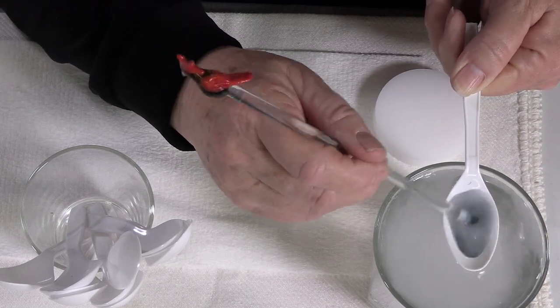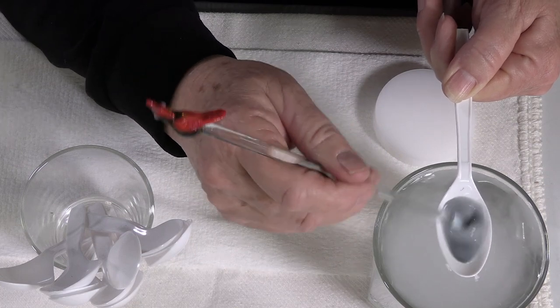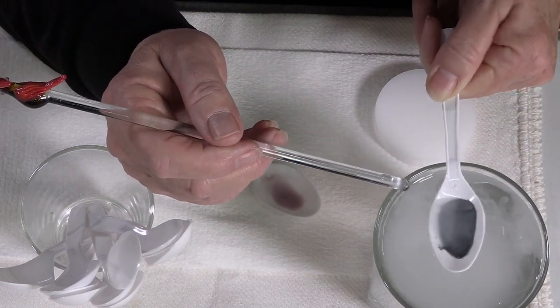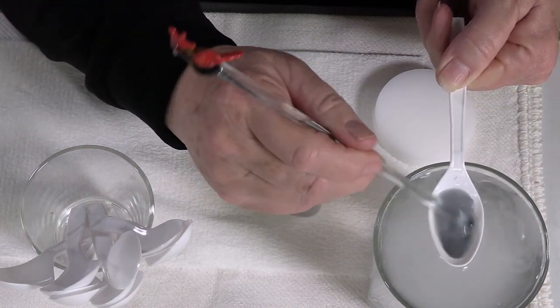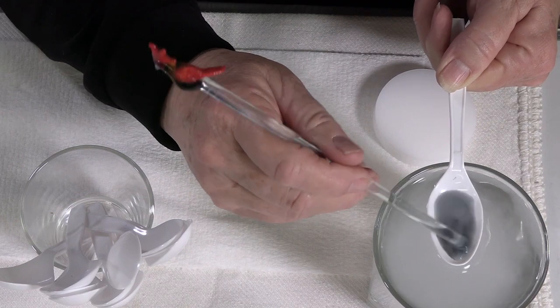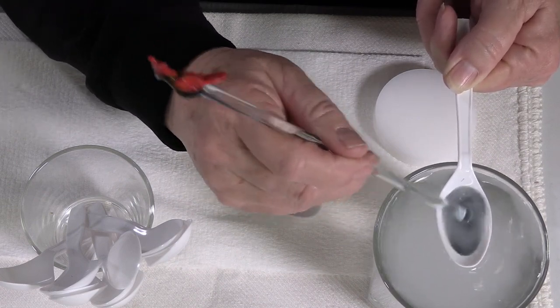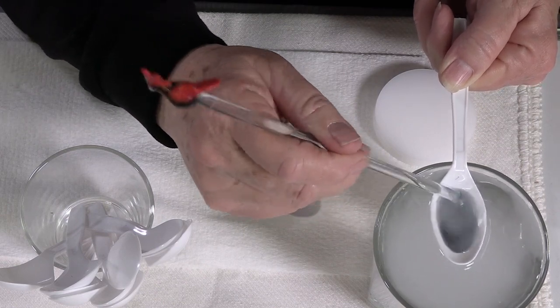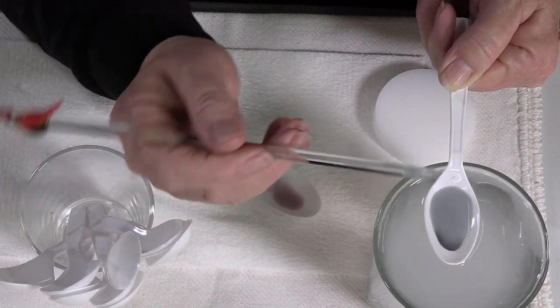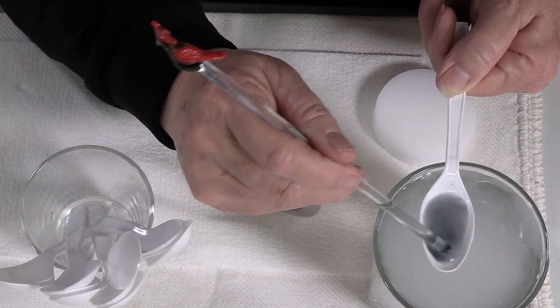I'm washing this darker color because in the darker colors, if it's not washed completely, you'll see a little pool of lighter colored enamel. With these Japanese enamels, because they're so clean, what I'm washing out of here is the super fines — like stuff that is maybe 500 mesh or something. I'm trying to leave the 325 mesh because I do so much shading and enameling in tiny little tight spaces that I need those small grains. As long as you don't apply your enamels too thick, those tiny grains are not going to cause cloudiness or bubbles in your piece. If you pile them on real thick, you could experience some cloudiness — but even 80 mesh is going to cause cloudiness if you pile it on too thick.